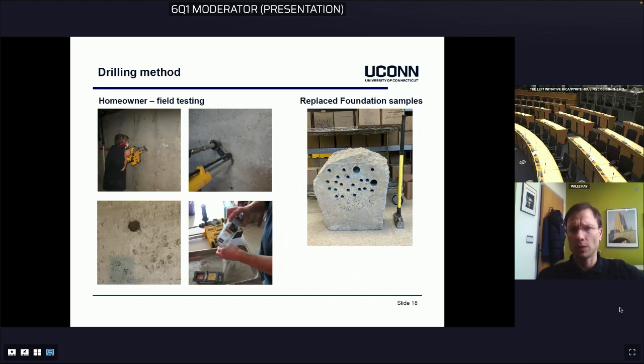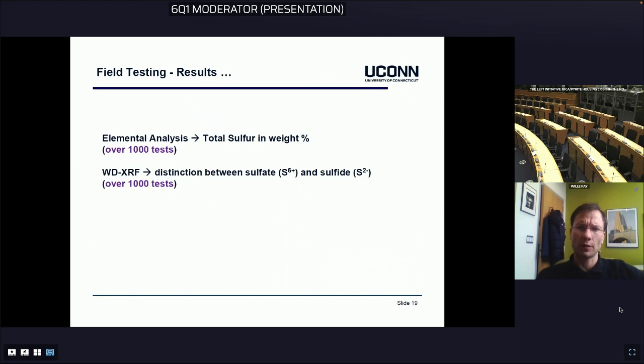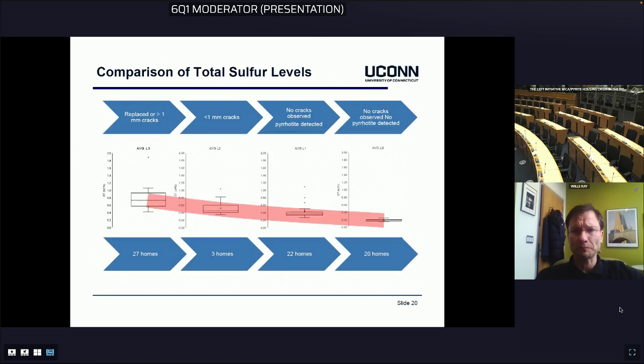Next slide. We collect the powder from the drilling with a vacuum drill, and then we analyze this powder in the lab, for example for total sulfur. We have done over 1,000 tests, and we also analyze this powder as pressed pellets using WD-XRF to distinguish between sulfates and sulfides. Next slide.